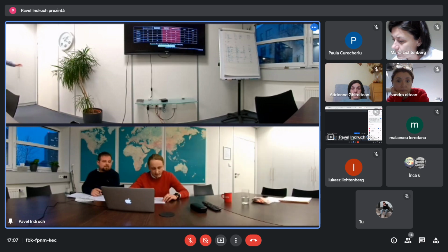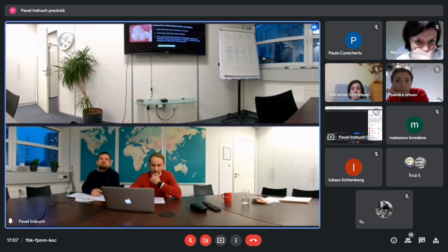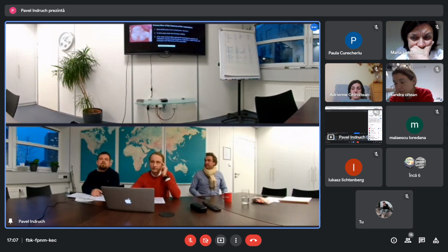composite restorations. This is associated mainly with the uneven stress distribution in the restoration and the effect of stress concentration. If the level of stress exceeds the load-bearing capacity of the restorative material or remaining hard dental tissues, this can be caused either by cyclic loading or accidental trauma. Cracks can initiate and propagate until the failure of the restoration. I bet that you already know a picture like this from your clinical practice, because it's a very common failure.